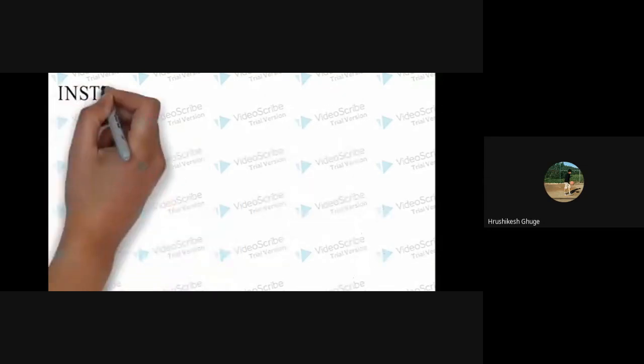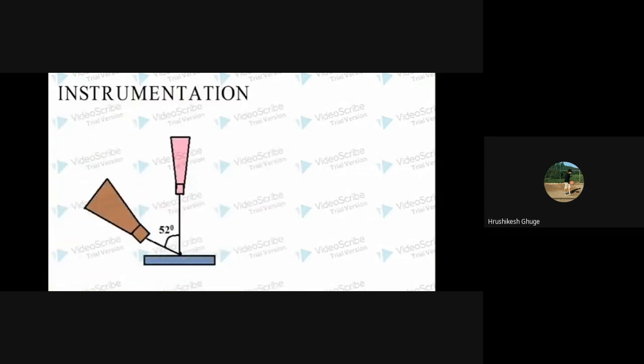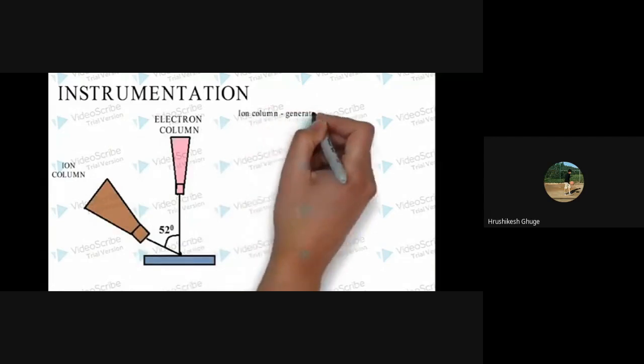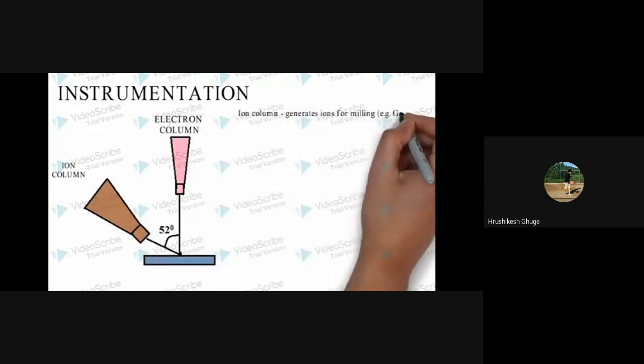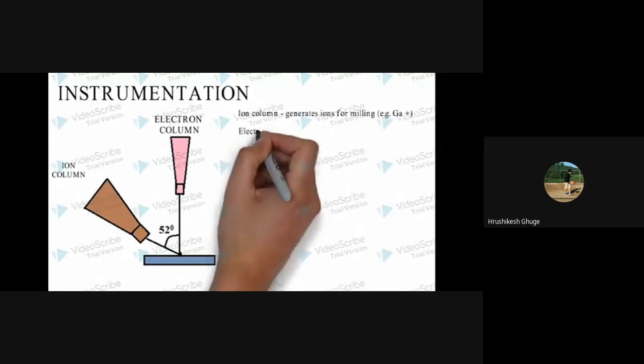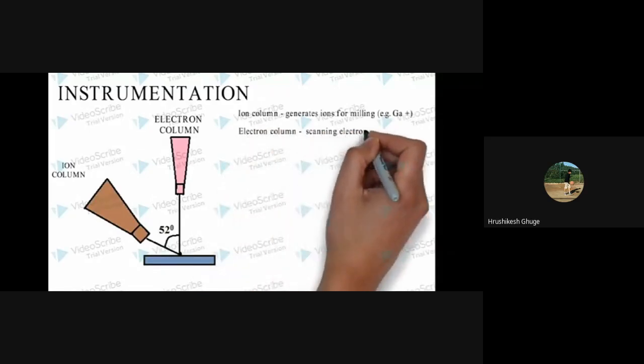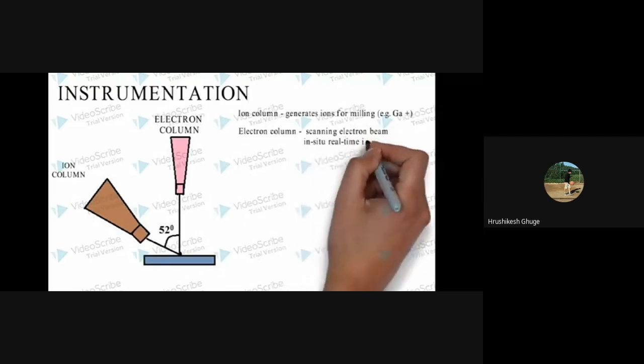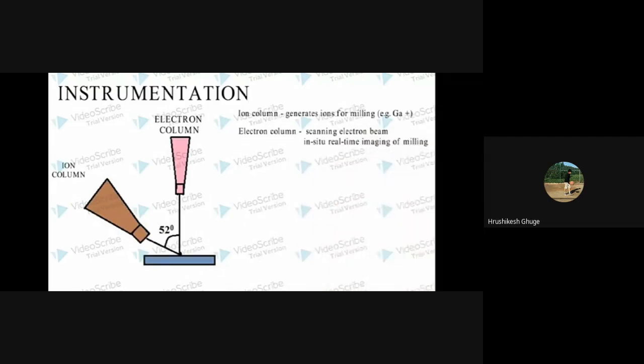Let's move on to the instrumentation of focused ion beam machining. Commercial FIB platforms incorporate both a focused ion beam column and a scanning electron microscope column, in which the ion beam column is used to generate the ion beam, which is used for machining the substrate or workpiece, and the electron column generates a beam of electrons, which can be scanned over the workpiece to get an in situ real-time image for observing the FIB process at the target zone. Typically, the ion column is tilted at 52 degrees to the electron column so that the real-time image can be seen on the computer screen.